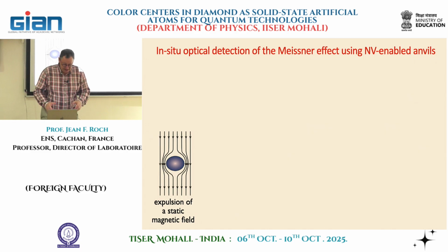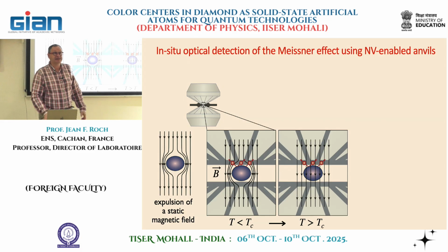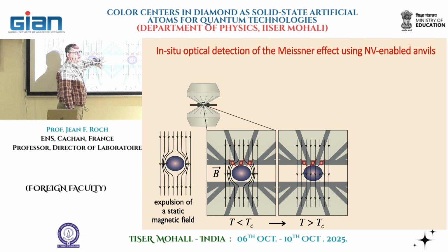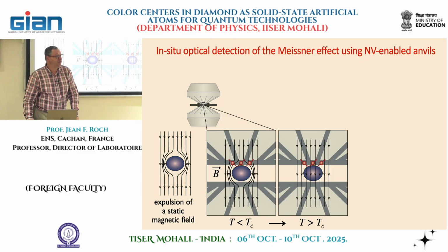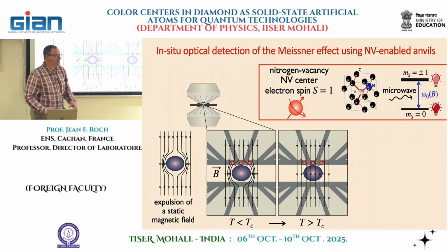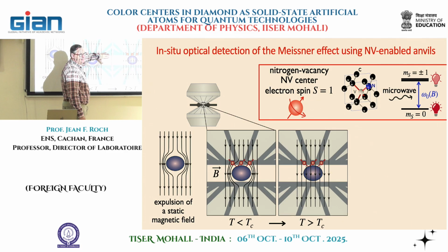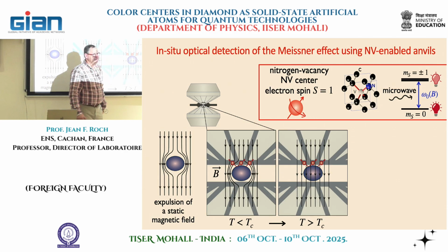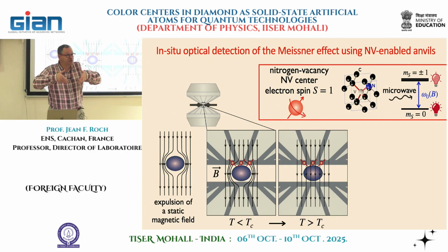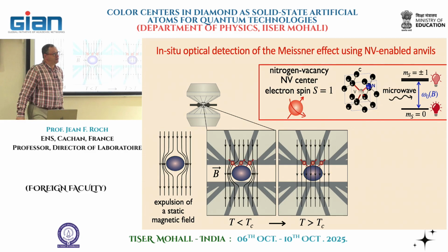So what we want to do now is to have some compass integrated or close to the sample that could be used to monitor the field distribution very close to the superconductor, and observe in real time, when we cross the critical temperature, that the magnetic field becomes uniform all over the sample. And for that, of course, you may have imagined, what we want to use is to integrate the NV centers and use them as in situ magnetic sensors on the anvil tip, to measure this distribution of the magnetic field. And that will allow us to really analyze how the magnetic field interacts with the superconductor, and that avoids all kinds of bias that could exist.